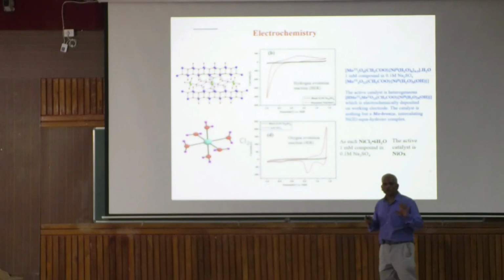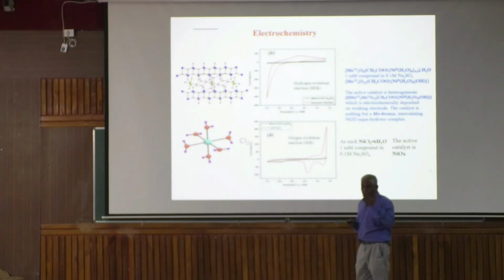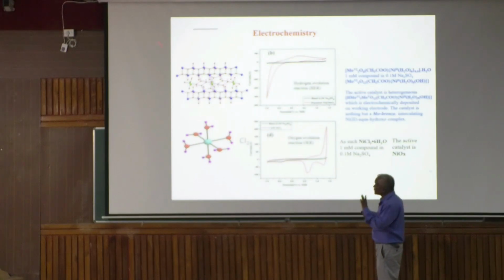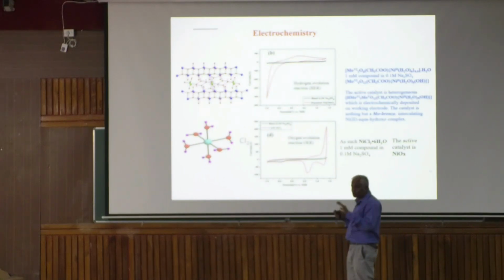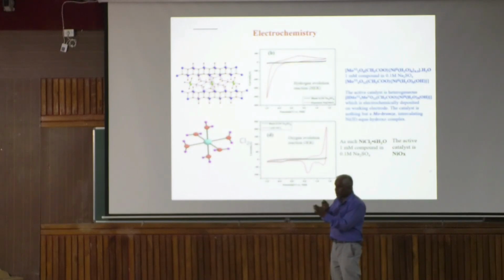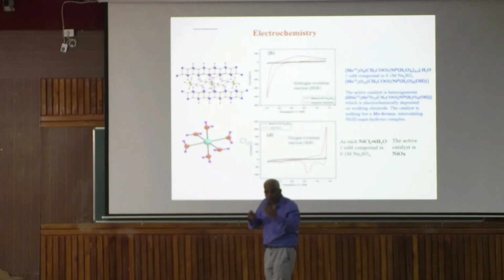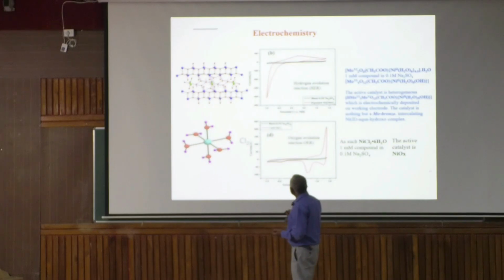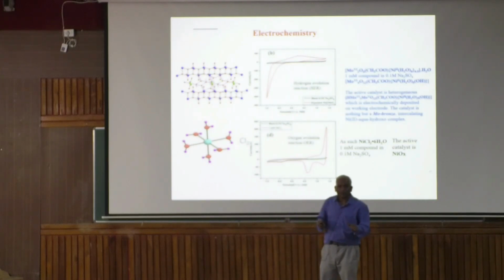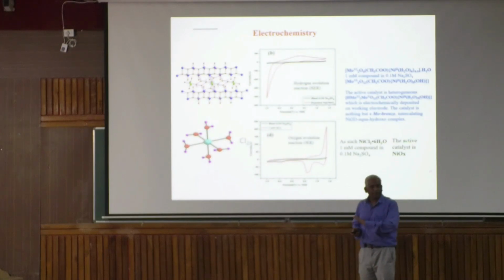That means, again, one has to do a computation study, theory, we did not do that. By logic of inorganic chemistry, what we explained when the reviewer asked is that due to strong hydrogen bonding, the electron density around the nickel gets reduced. The electron density drifted from the metal side goes to the hydrogen bonding. So the nickel center becomes electron hungry, prone to be reduced, isn't it? So that's why maybe it reduces easily, nickel 2 to nickel 1, and gives the hydrogen reaction. Again the question comes, so nickel 2 may go to nickel 0 because we are getting hydrogen evolution. We did a control experiment, we did not get any nickel 0. It is always nickel 2.